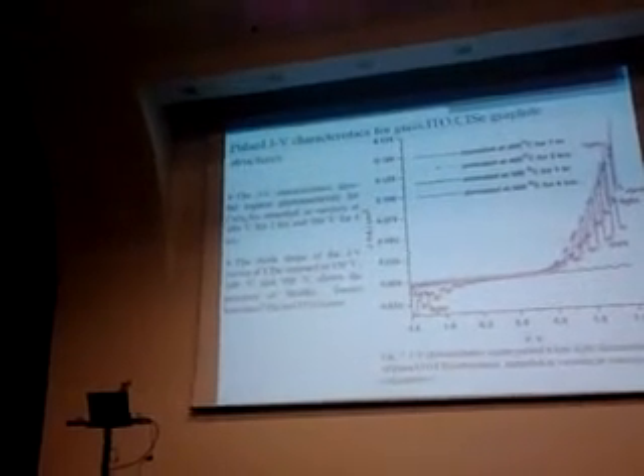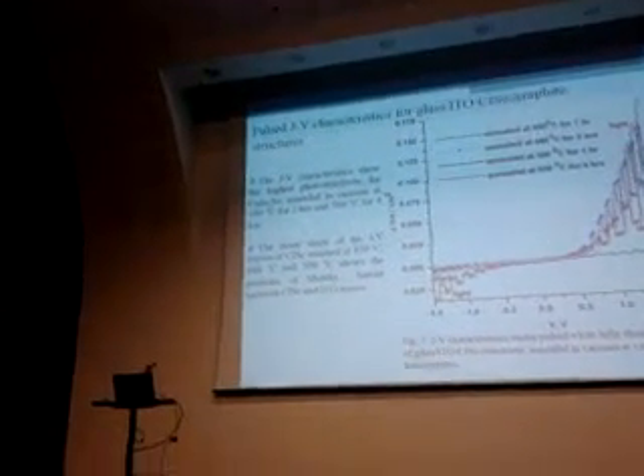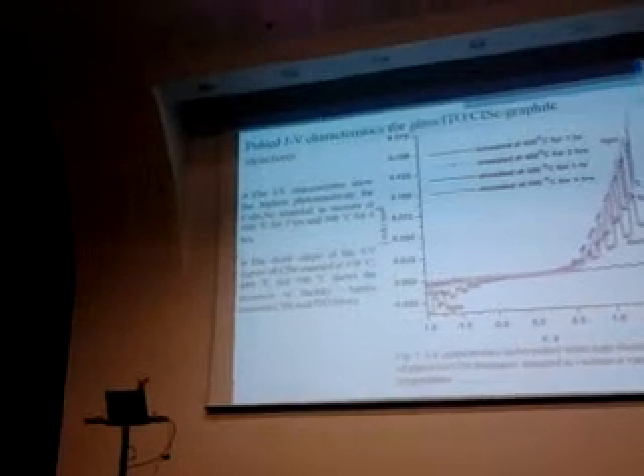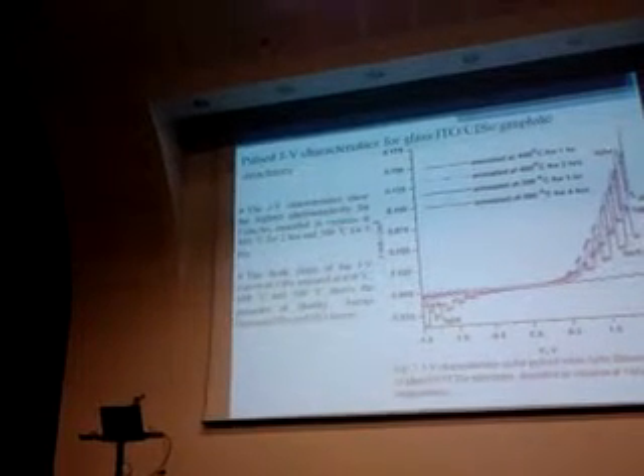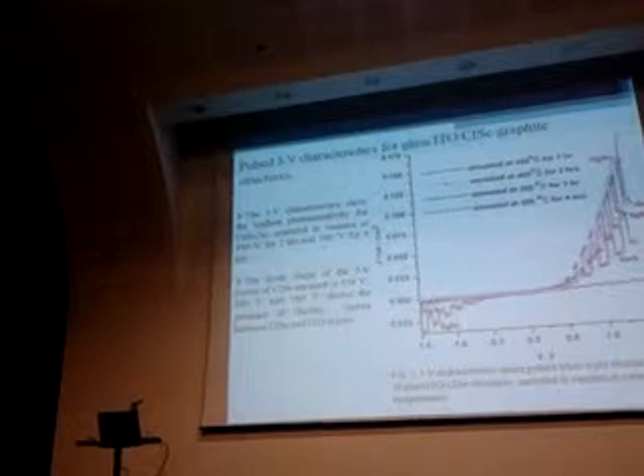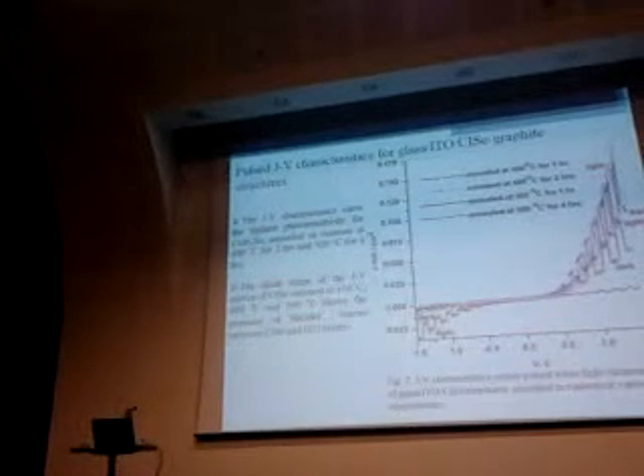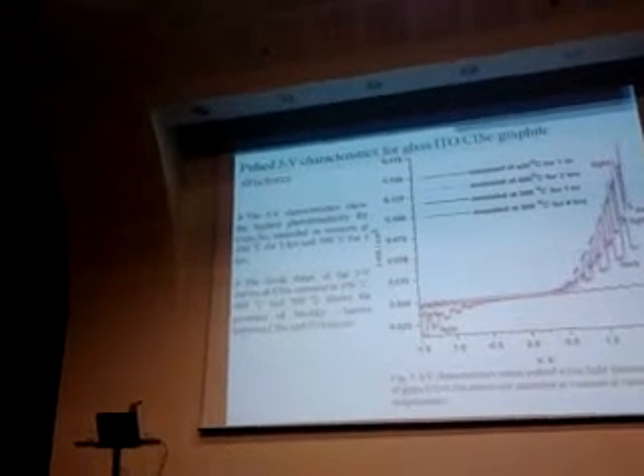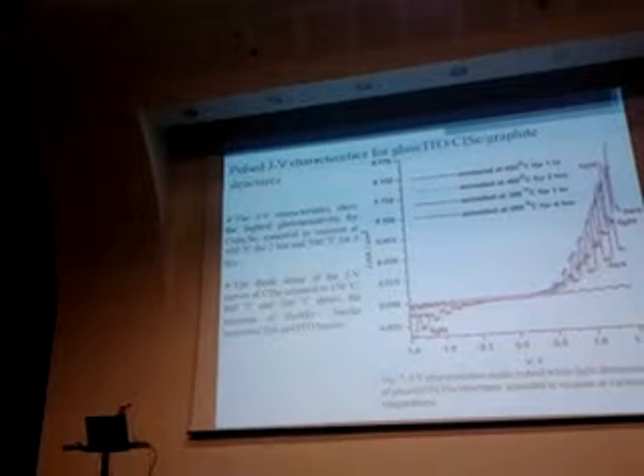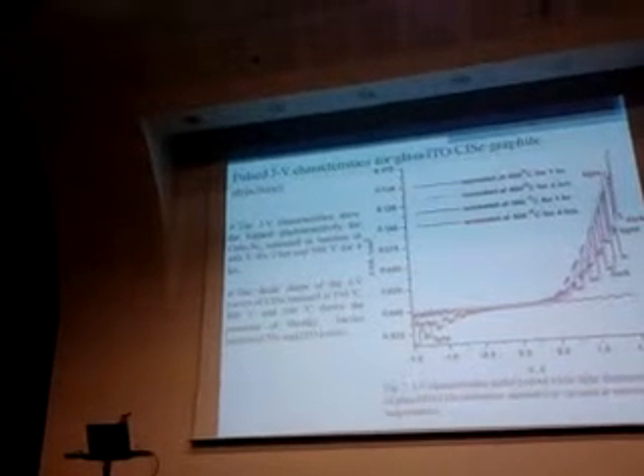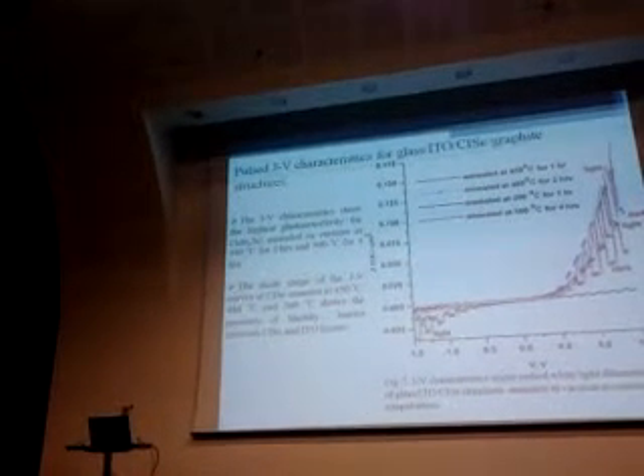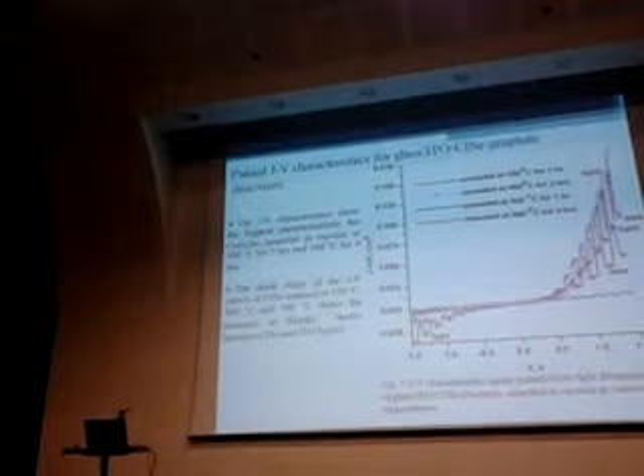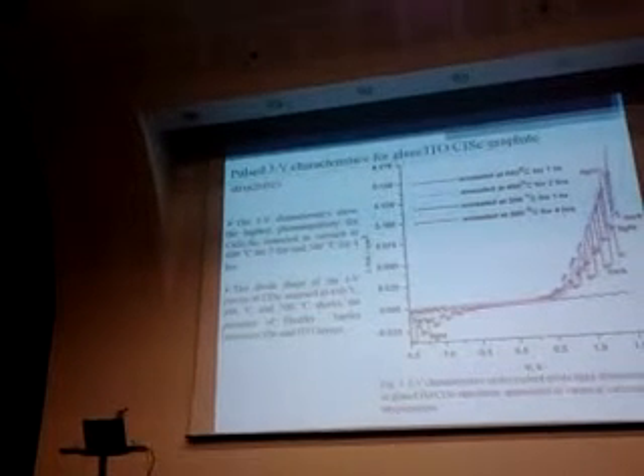In another way, if we measure only the dark current and the light current - this portion is the dark current and the other is the light current - we see that the change between dark and light current, the relative photosensitivity, goes on increasing. From this graph, we conclude that the CISe layers annealed at 500 degrees centigrade for 4 hours show the highest photosensitivity.